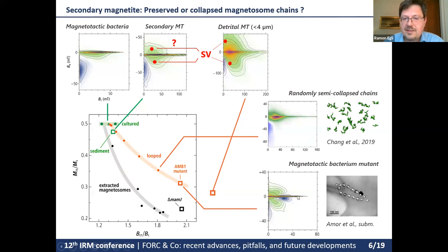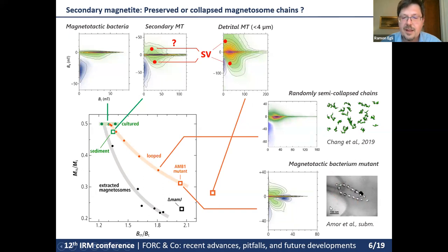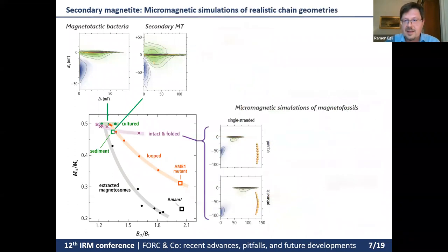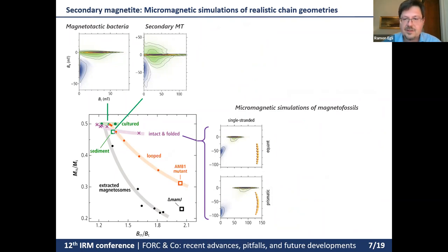At the end of this trend, together with colleagues from biology, we get the signature of bacteria that produce magnetosome loops. These loops create flux closure patterns with the signature of single vortex particles. Having these things in mind, I started to model chains of magnetosomes assuming that they will not collapse in the sediment — that they will preserve the original structure as produced by magnetotactic bacteria. These structures are actually very different.